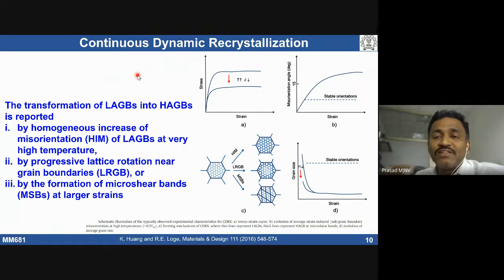Because dislocation density has not come down, we are still increasing it. So that can lead to fresh nuclei forming, a strain-free grain forming which has a high-angle grain boundary character. If a strain-free grain forms with a high-angle grain boundary character, that is called a recrystallized grain. So this is the difference because of stacking fault energy difference. How the final recrystallized grain develops is going to depend on the stacking fault energy of the material. With higher stacking fault energy, we see first recovery followed by recrystallization. With low stacking fault energy, we directly see formation of recrystallized grains.